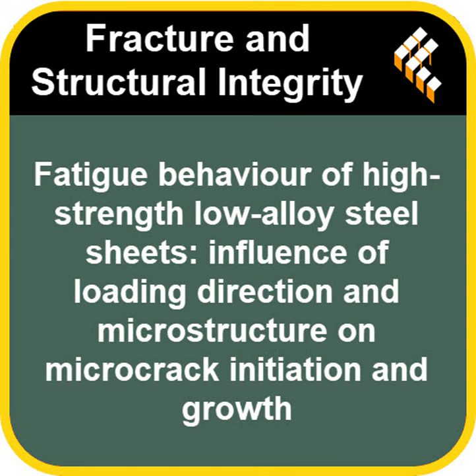Critically, cementite sitting on these boundaries seems to do the opposite of strengthening. It reduces the boundary's ability to accommodate those dislocations piling up. It weakens the boundary's resistance to cyclic stress. So this intergranular cementite acts as a preferential site for cracks to start and grow, especially at higher strains. It's like a weak link in the chain, and it seems to be a major reason why TD performs so poorly in fatigue.